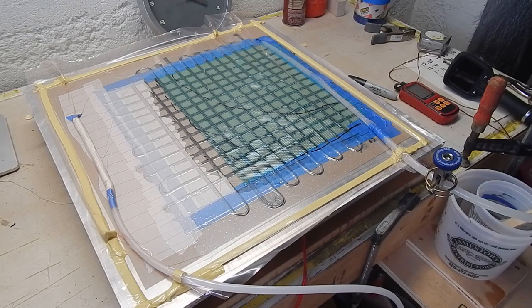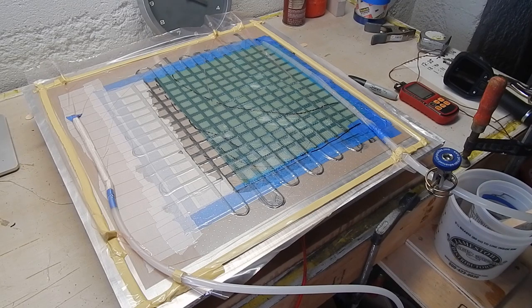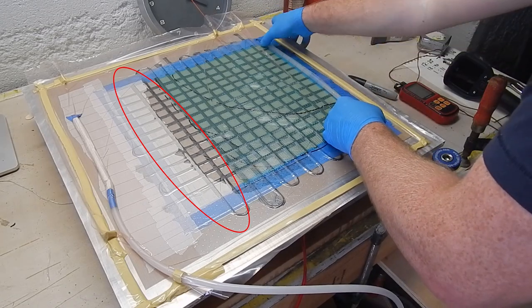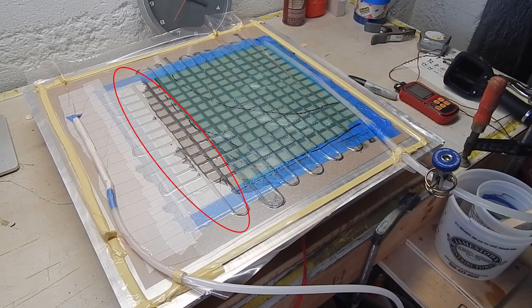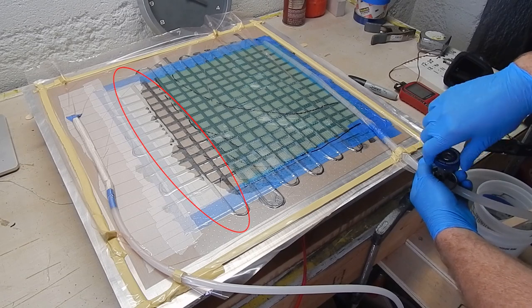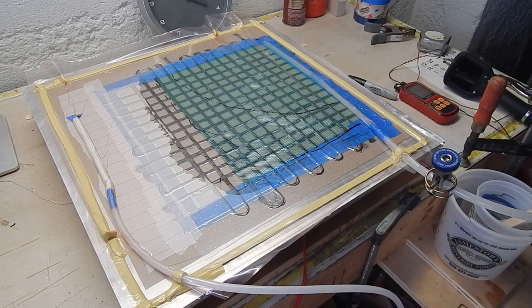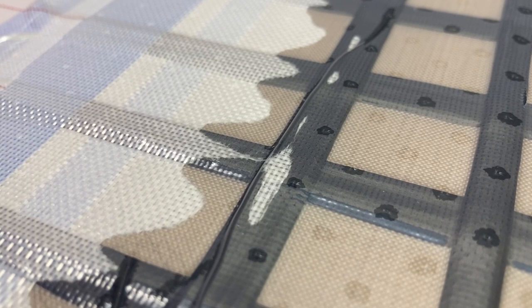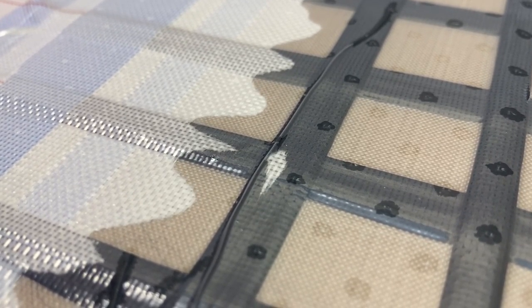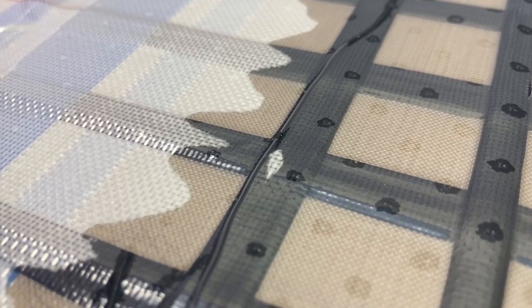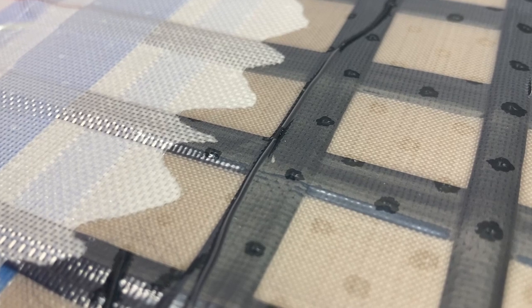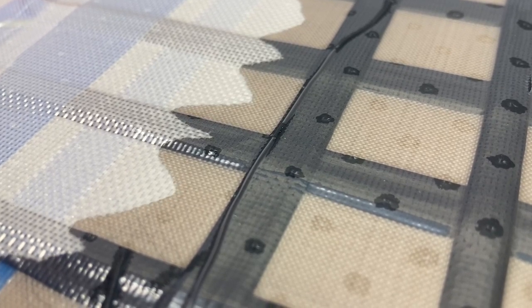It's filling all of this really quickly and nicely. Coming up to the end of the panel. Holding back the flow media like that is really important. It provides a flow break and allows it to equalize before it reaches the end of the part. You can see it filling in those tows here. Sometimes tow is hard to infuse in big bundles, but here it's worked out pretty nicely. These are small enough that the resin just fills in if given enough time.